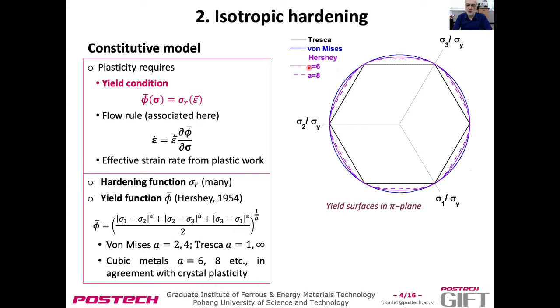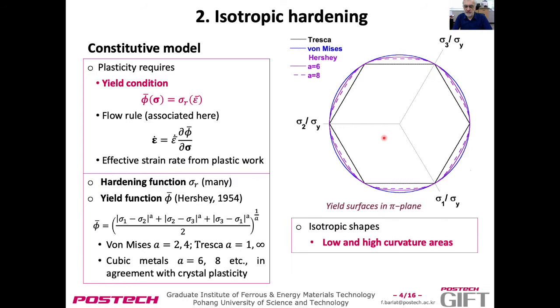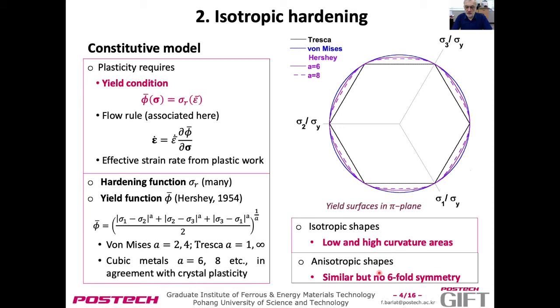What we see from this figure is that in Tresca—except for von Mises—we have areas of low curvature and areas of high curvature, like in the corners or vertices for Tresca. For an anisotropic material we would get something similar, but without the six-fold symmetry that we have for isotropic materials.